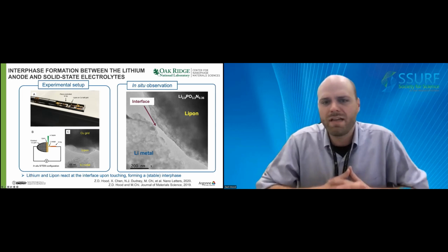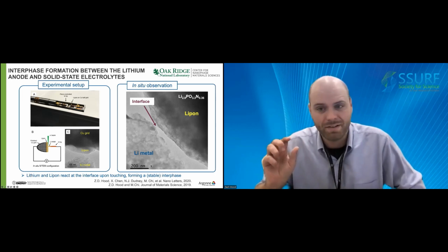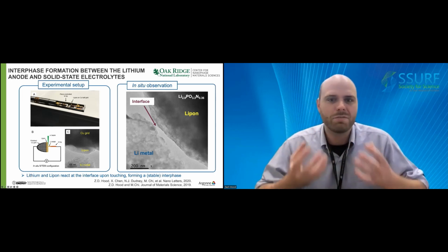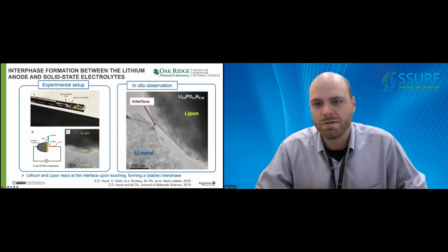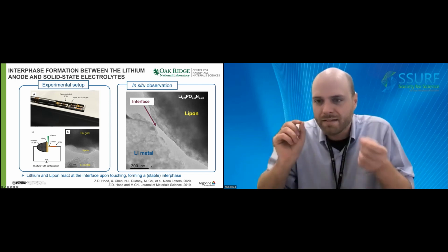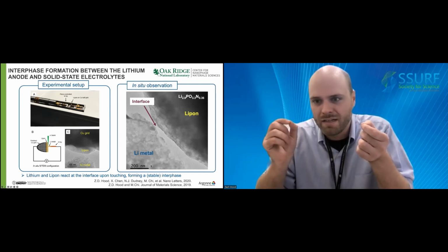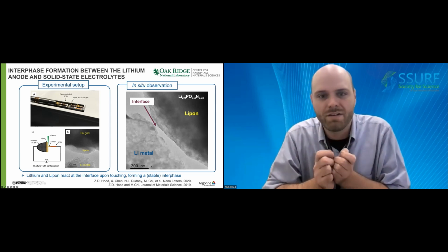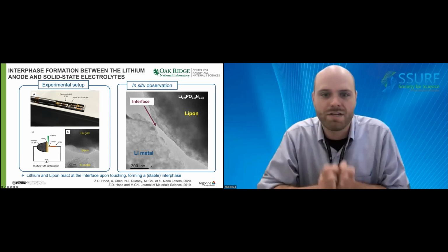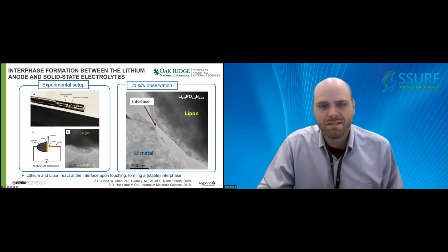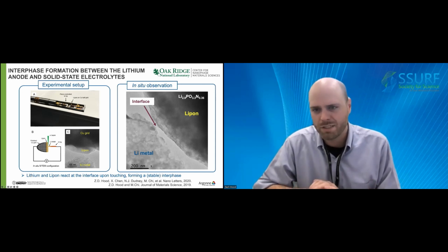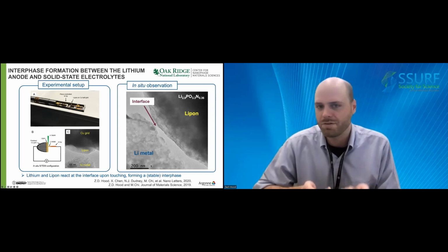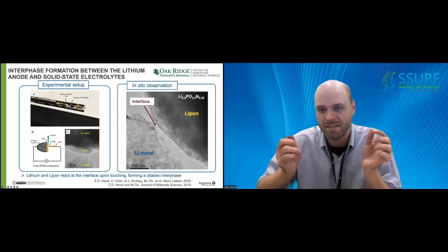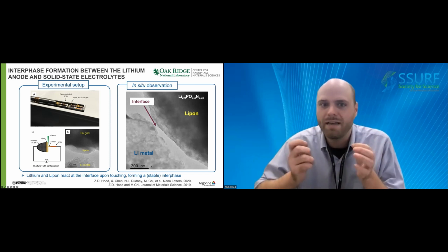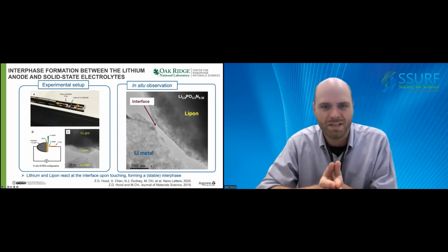And so to interrogate this interface between the lithium metal anode and LiPON, we developed a novel method to look at the interface by touching lithium metal and the LiPON solid-state electrolyte in situ at the Center for Nanophase Materials Sciences at Oak Ridge National Laboratory. Here, we applied transmission electron microscopy using a unique piezo-controlled holder that allows us to directly touch the materials and apply an electrochemical bias across this interface.